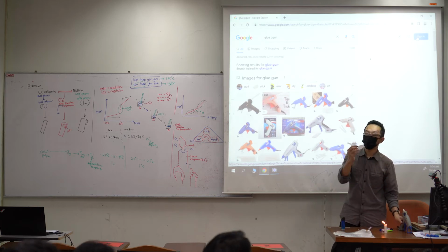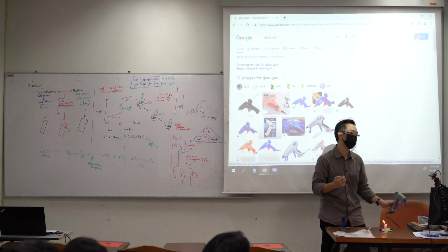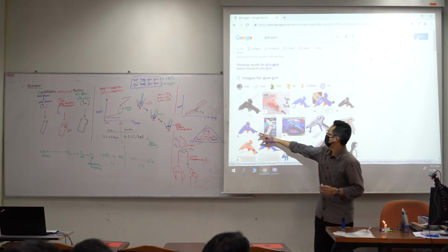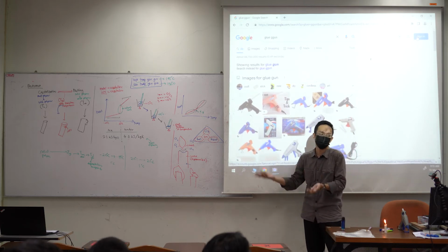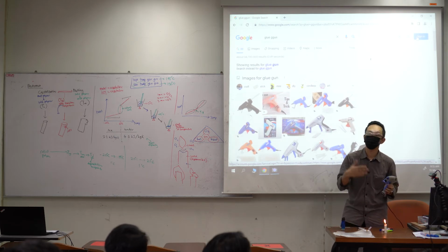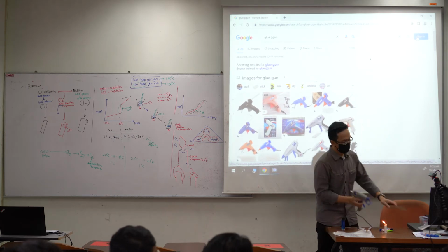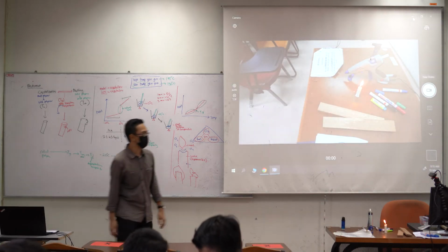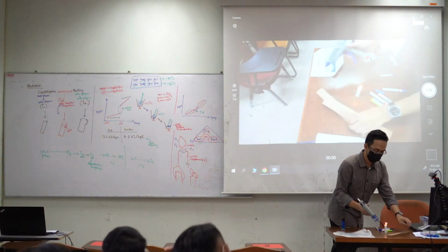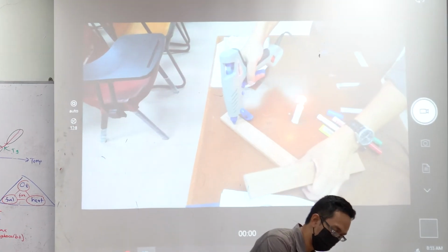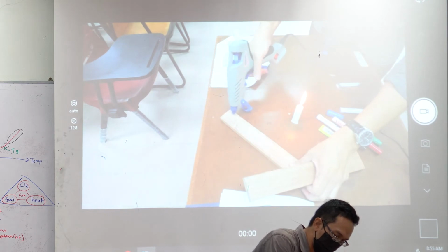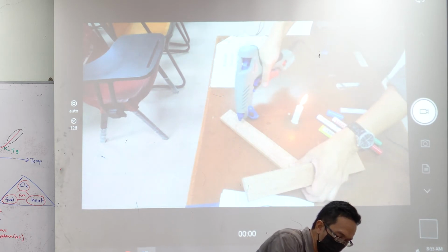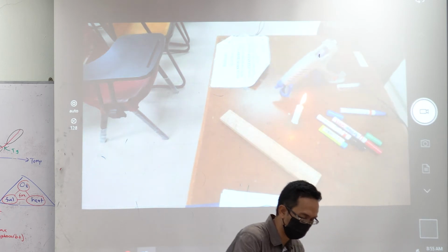One of the advantages of using the high temperature stick with the high temperature glue gun is that you can bond more materials. For example, this one can only bond maybe polystyrene, normal things. But this one can give a good bond even to metal or wood. For example, I have the wood here, and I try to glue these two pieces together. So I just do like that, and this is melting. This is melting at 165. It's not nice, but it's okay.